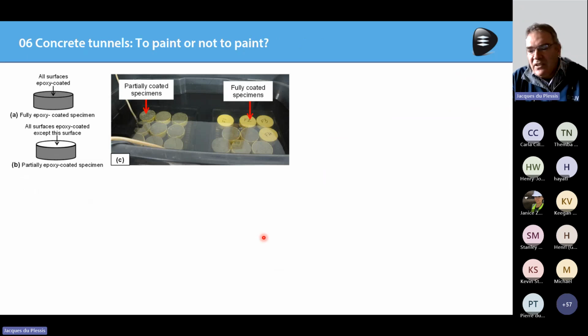Now, the concrete tunnels, the water at Ingula is very soft. So because of the soft water, you get soft water attack. And for a long time, it was debated whether it is necessary or not necessary to paint the tunnels, just to delay the soft water attack and the degrading of the concrete of the liner of the tunnels. So in the laboratory on site, these specimens were cast and they were painted with epoxy paint.